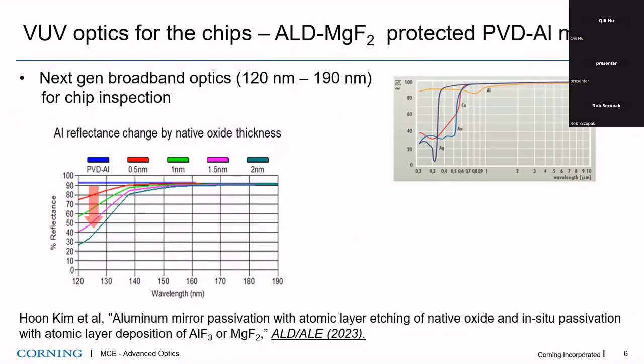Then we step up to VUV. That's the next generation for inspection systems. When the feature is smaller, you want to use shorter wavelengths, right? So the next generation is broadband, 120 nanometers to 190 nanometers, using a laser sustained plasma source. And in this case, the optics still need to be reflectors.